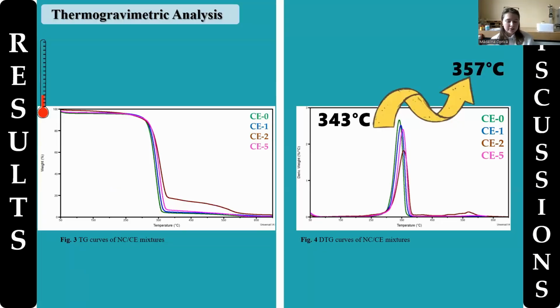The thermal characteristic of the nanocellulose and curcumin extract samples are presented in the TG and DTG curves. We can observe an increase in the thermal stability brought by the addition of the curcumin extract, with a little over 10 degrees between the control sample at 343 degrees and the sample at 357 degrees.